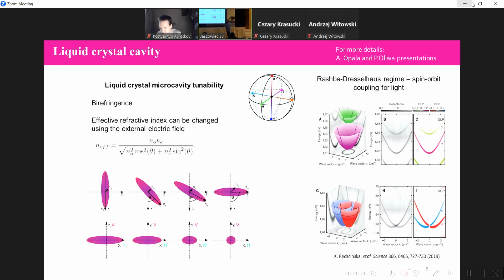But at room temperature, they have birefringence, and the effective index can be changed using an external electric field, not like in the perovskite on the previous slide. You can see when we tilt a liquid crystal, the optical path for vertical polarization stays the same, but for horizontally polarized light it changes. That means we can tune the horizontally polarized mode to the vertically polarized mode, which stands still in energy.